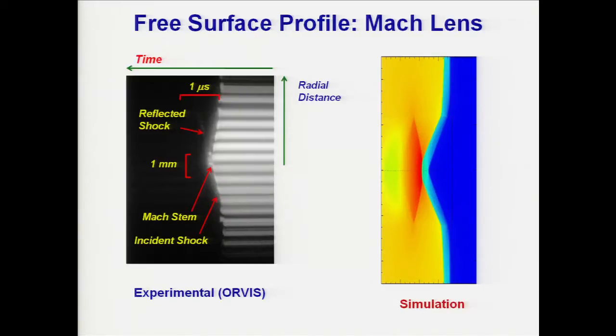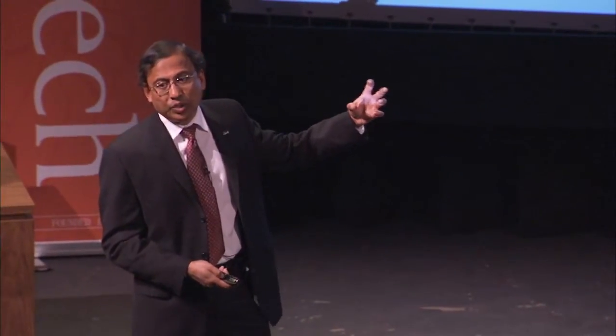We can also study the structure of the shock wave using the experimental device called ORVIS, which looks at the full profile at the back of the target. And this is the simulation which I showed you earlier. Here is the Mach stem, which is seen here. And these are the incident and the reflected shocks, and also the shock in the outer material. So we have validated this technique for achieving high pressures. Now we can take this technique and use it in any range of velocities. In this case, we have shown it at about 2 kilometers per second.